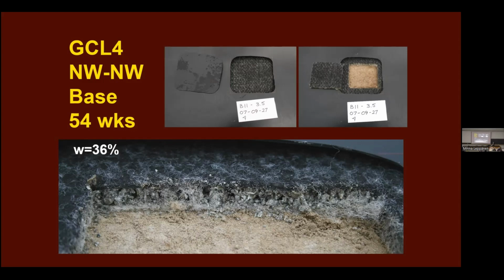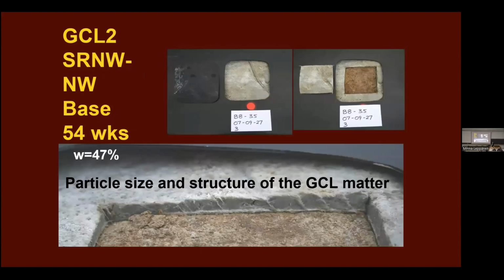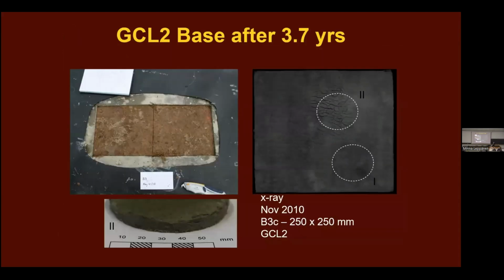Now, if you start to hydrate, you then put it in a landfill or a mining situation and permeate it with a fluid, there'll be orders of magnitude difference in the hydraulic conductivity of those 2 GCLs because of their starting position and their history. Just look at the other one. Compare the 2. Now, as I said, GCL2 is just starting to desiccate, but when it was tested with a permeant that simulated landfill leachate, it still had very good hydraulic conductivity. So the history of what it goes through affects what its long-term performance is.